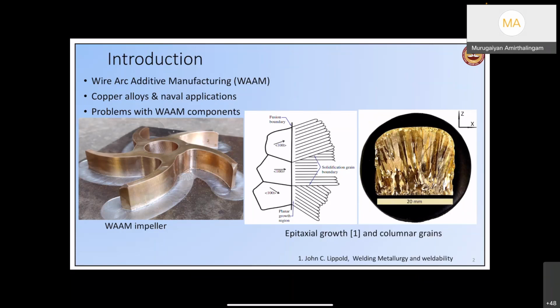And if we use a component containing such a microstructure, and apply a load perpendicular to it, here in the z-axis, it would just crack. It's like wooden plywood, isn't it? When you take a plywood, in one direction you can break it easily, whereas if you break in another direction, it's very difficult, isn't it? Because of the preferred orientation of the wood fibers inside. The same happens here as well, and this is what we call anisotropy.